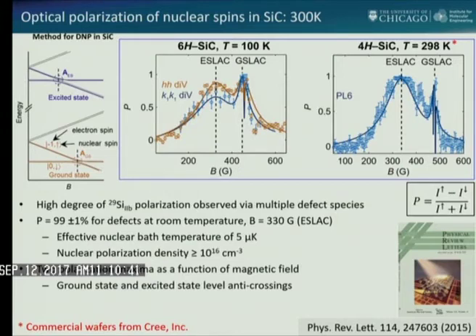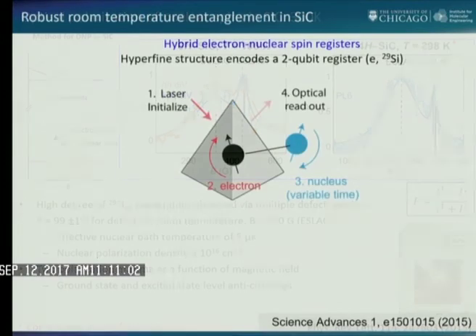So we're working very hard with now some of the imaging groups at Chicago to try and use these as high contrast imaging agents in radiology, where we're doing some prototype experiments to polarize these and then inject them in systems, because now they're getting 10,000-fold larger signals than you would get before. There's still lots of challenges, but it's an interesting direction.